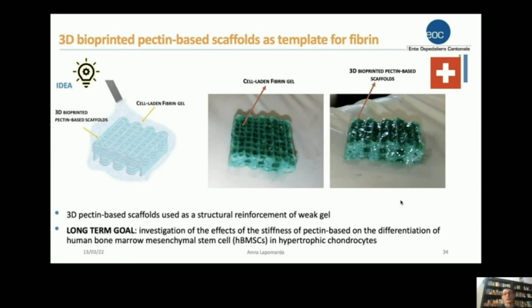The other approach that we explored with this material is using the pectin structure as a template for fibrin gel. So we construct the pectin and then we cover it with a fibrin gel where we embedded human bone marrow mesenchymal stem cells in order to study the formation of cartilage inside this structure.